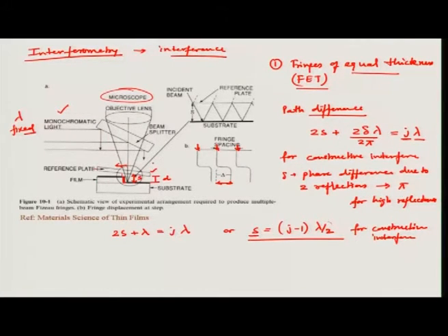So, as you are scanning in this direction from right to left, you observe the change in the fringe spacing under microscope, and from this delta you can calculate the film thickness D as delta over fringe spacing into lambda by 2. So, this is your film thickness.